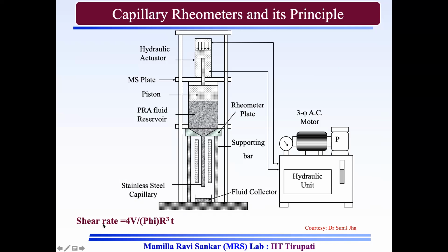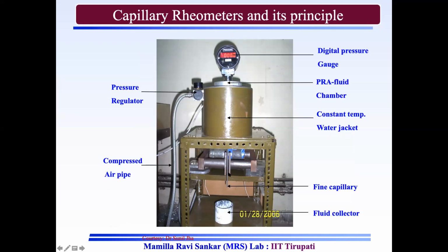That means the shear rate equals 4V by πR cube into T, where V is the volume of material that you are collecting in the collector, T is the time, which is nothing but the discharge, and R is the radius of this particular tube. Normally in practice how it looks is this. This particular tube normally will have an L by D ratio of more than 1:18. That is a normal thing on the rheological aspect. If at all you want to know the basics about rheology, you can study the book by Professor Macosko.